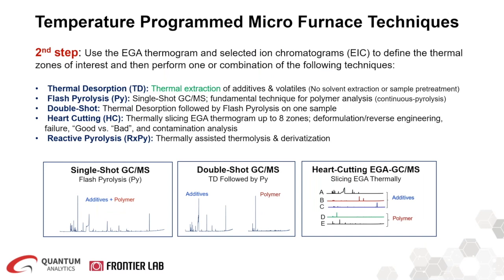After obtaining the EGA thermogram, you can analyze the peaks using the F-Search EGA MS library. If it's needed to further analyze the sample, EGA guides you to the next step. You can perform thermal desorption, which is used for analyzing additives and volatiles. However, the key point here is that you are thermally extracting the additives and volatiles from the mixture. So any sample preparation or solvent extraction step is eliminated. You could also perform flash pyrolysis, which is also called single-shot GC-MS, and it's a fundamental technique for polymer analysis. In this mode, the furnace is typically programmed at high temperature to break down the polymeric and heavier compounds into smaller fragments.